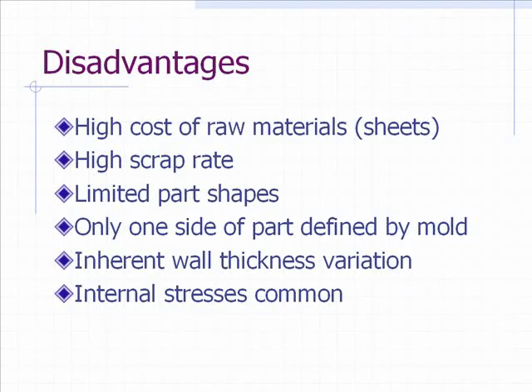you'll see down in the corners is where it stretches the most and it becomes the thinnest. This mold right here is a mold that you would make for packaging, say for cookies or something like that. And if you get cookies like that, you notice that in the corners there, they'll tend to be much thinner. That's where they'll break. That's because it stretches more in that area than it does on the sides there. So it has inherent wall thickness variation.